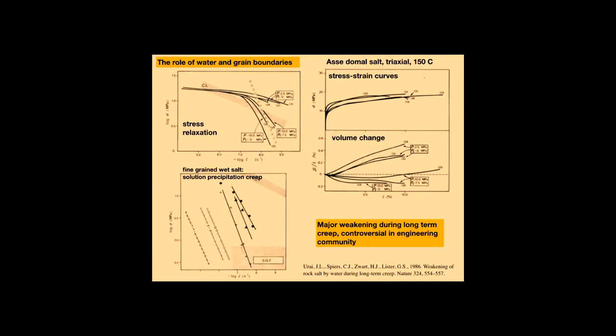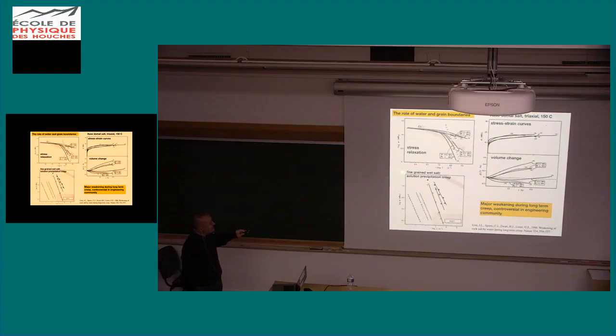So that inspired us to do another set of experiments where we made artificial fine-grained rock salt, so really small grain sizes, and then made them wet with a small amount of brine. The steady state strain rate of these salt samples was much faster at the same stress than ever found before in sodium chloride work. So we found a major weakening during long-term creep under these conditions.